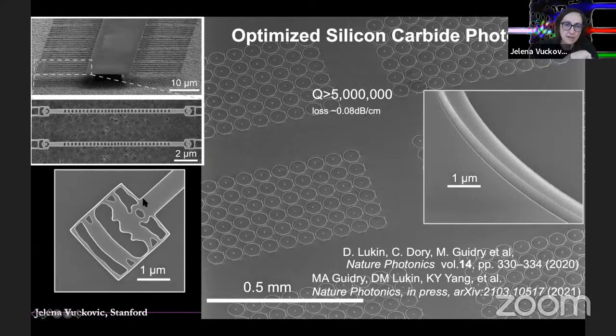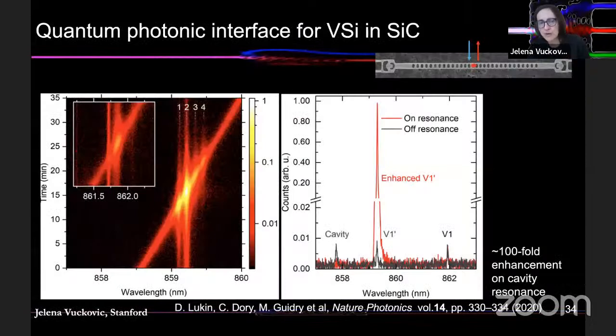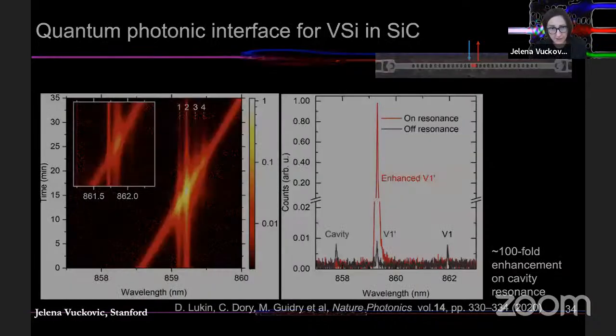We're also able to make inverse design structures, resonators. And these are also suspended structures, or you can leave them sitting on this oxide layer, which is a lower index layer. And that way you can actually have high quality structures. So there are more pictures of resonators shown here. You can do all of that without sacrificing properties of the color center. Again, silicon vacancy transition, tuning relative to cavity resonance, or actually in this case, tuning cavity resonance relative to different transitions. And we can enhance on resonance by a very large factor. So properties of the color center have not been sacrificed in the process.